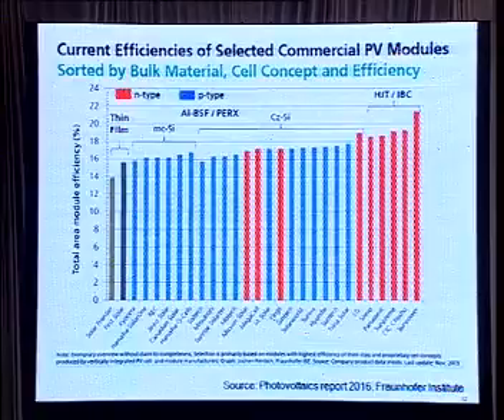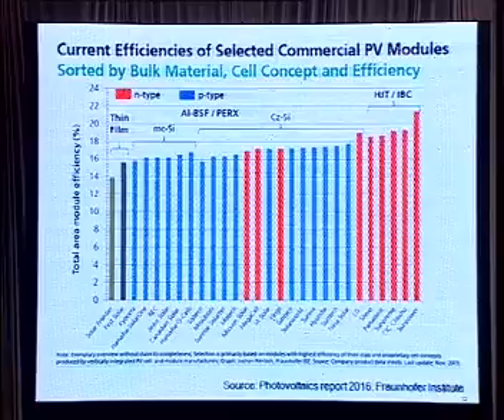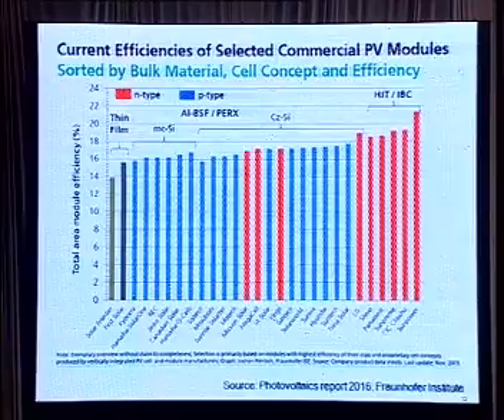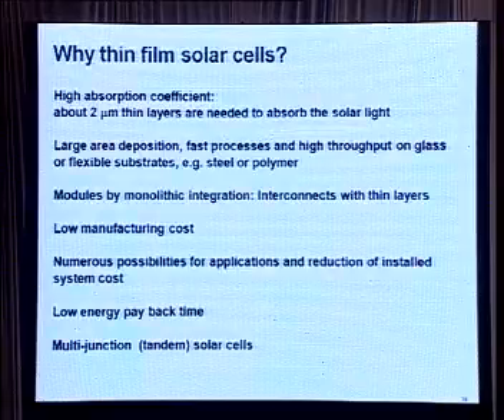These are some of the typical efficiencies of single crystal, multi-crystalline, and thin films. So you see that typically thin film modules are somewhat lower in efficiency, but there is a good reason to work on that. The efficiency of thin film is roughly about 14 to 16% compared to multi-crystalline silicon, which is 16 to 18%. So roughly about 2 to 3% efficiency gap. So why one should work or think of thin film solar modules?